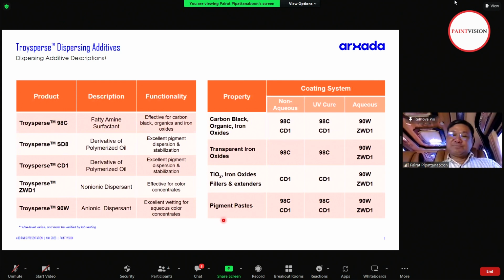This is the selection type of the system, either non-aqueous, UV, or the aqueous system, with different kinds of pigment that you may select, and also which dispersant that you select for them. Just to make sure, when you use a solvent-based system or the UV curable, CD1, SD8 for the inorganic pigment, 98C for carbon black and organic pigment. For aqueous water-based, mainly ZWD1, and also you can use 90W as a wetting additive for the excellent property.